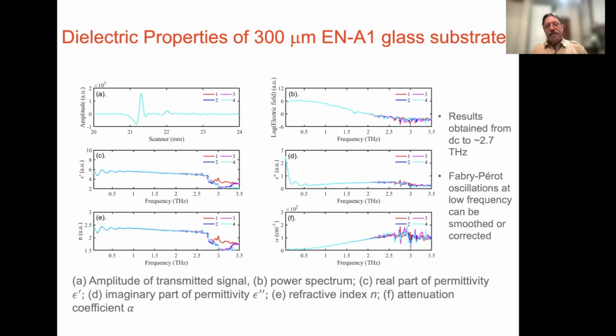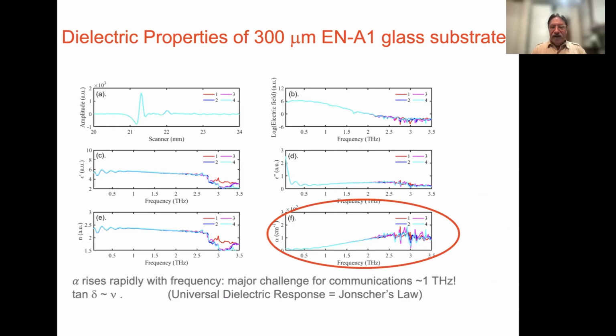So this is something that is not fully appreciated by many people, that many materials become very lossy at hundreds of gigahertz and at terahertz frequencies, materials that people call low loss for millimeter wave applications. So here's those growing losses. This is actually a physical effect that's been studied for many years, not always very well understood. It's called either the universal dielectric response or Jonscher's law. This growth is in the absorption coefficient; the refractive index, though, is pretty flat.